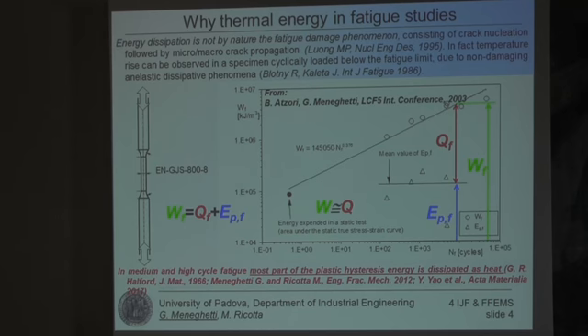Now, we measured also with a special technique the heat energy dissipated by the material, and so for a given total number of cycles to failure, we had measured the total mechanical energy expended to break the material. We measured the heat energy dissipated during the fatigue test, so by difference we could estimate the energy stored inside the material up to fracture. And you see here that the mean value of the total energy stored inside the material is in good agreement with the energy expended in a static test.